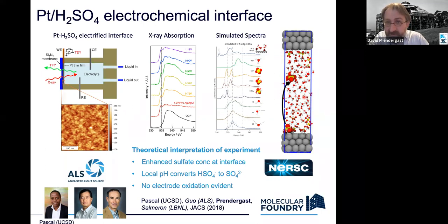Let's say down to about here is about 1 nanometer. And so what we're expecting in this experiment is that it's sensitive only to the oxygen atoms in this region. If there were an oxide on the platinum, it should be very sensitive to that, because if the oxide builds up on the surface, it's even closer to the electrode, and it's the actual electrode that detects the signal. So let's say I excite an oxygen here, it goes into an X-ray excited state, and then that state decays or relaxes and emits an Auger electron that might be detected in the electrode or might be neutralized by an electron coming in. It depends on how the process works.